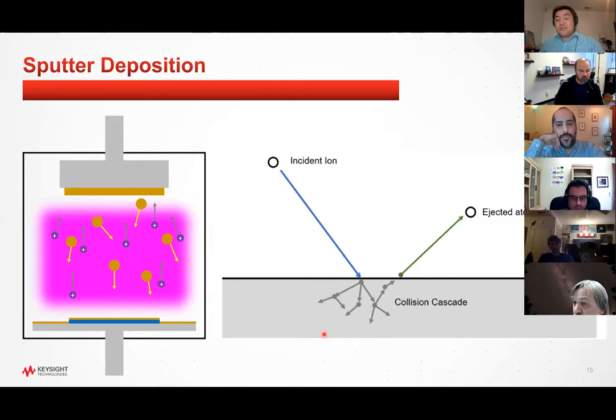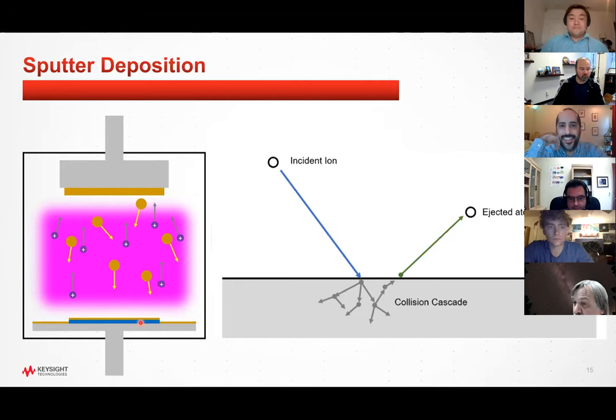You get this collision cascade of different atoms bumping into each other, and some proportion of the time you're going to get an atom of the target material getting ejected from the surface. And then these will go around the chamber and deposit in a thin film on your sample, and unfortunately also oftentimes all over the rest of the chamber. But you're able to produce very thin films using this method.